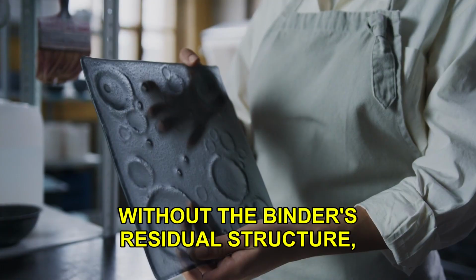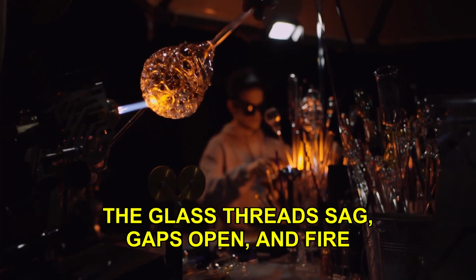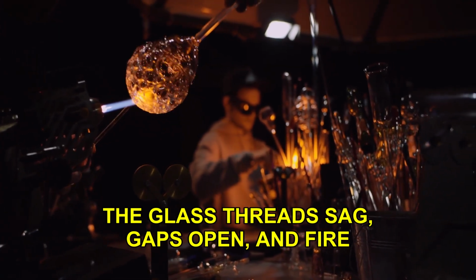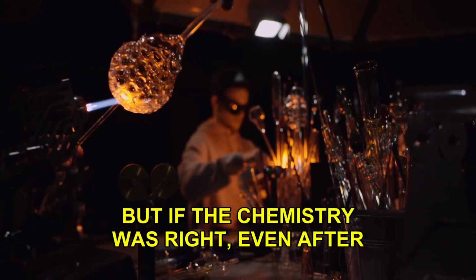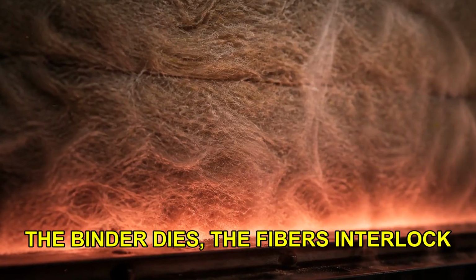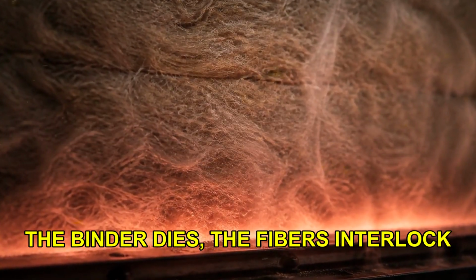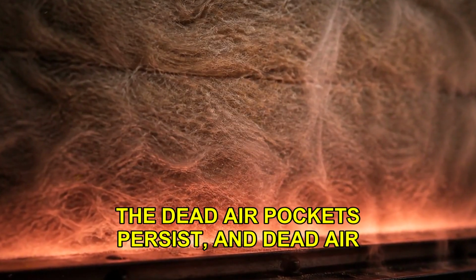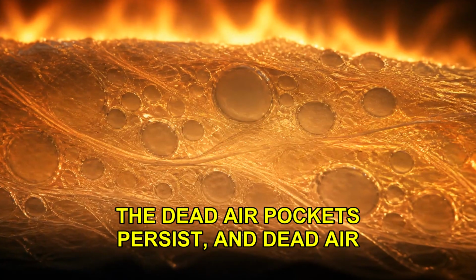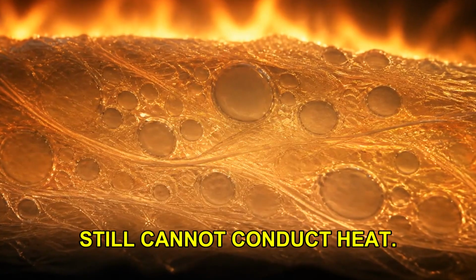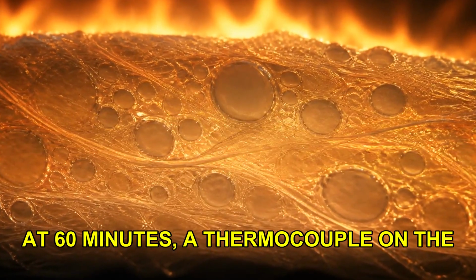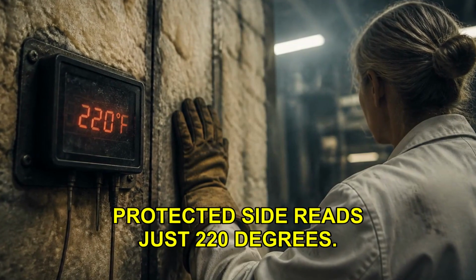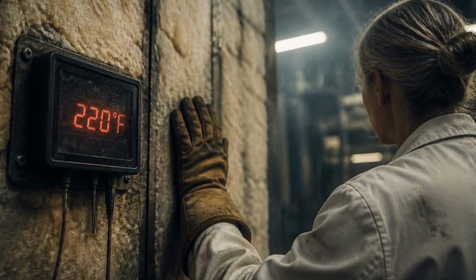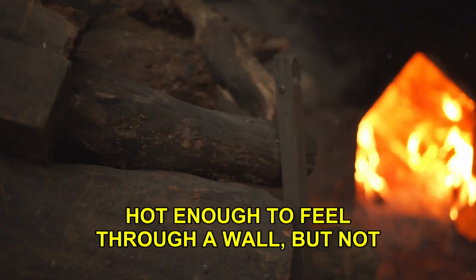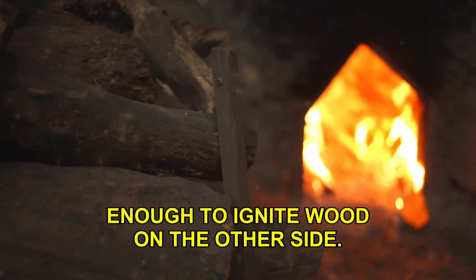Without the binder's residual structure, the glass threads sag, gaps open, and fire punches through. But if the chemistry was right, even after the binder dies, the fibers interlock enough to maintain a barrier. The dead air pockets persist, and dead air still cannot conduct heat. At 60 minutes, a thermocouple on the protected side reads just 220 degrees. Hot enough to feel through a wall, but not enough to ignite wood on the other side.